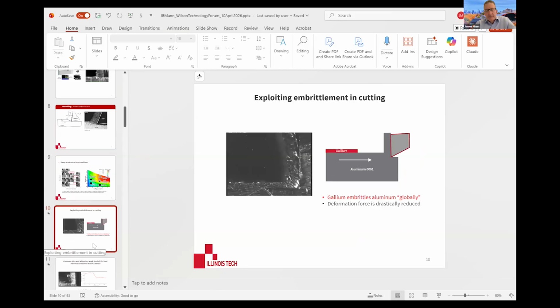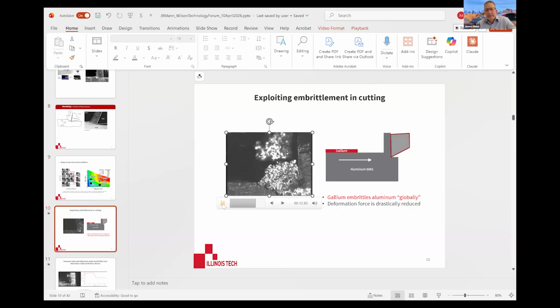Another aspect of what we're working on in our research today is exploiting embrittlement in cutting. And this video is an example of liquid gallium exposed onto an aluminum workpiece. And the gallium actually absorbs into the workpiece and has a drastic influence on the deformation mechanics. And so I'll show another video. And this is normal cutting, and then it's approaching the area where the gallium is. Now you see the radical transformation in the cutting process.